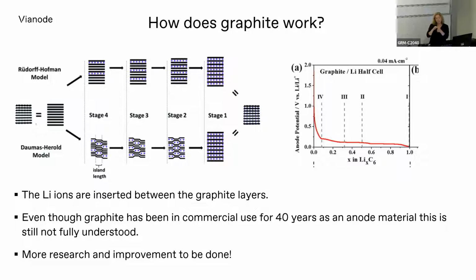And so when you push the lithium ions into the graphite, it goes between those layers of sheets and it sits right in the middle of that ring of atoms. And then that allows it to be stored in a very stable way. So what makes graphite work so well as an anode material is that you're only moving the sheets of carbon atoms a little bit apart every time you charge and discharge. And so the fundamental structure of the material is not changing. So that's what's called an intercalation material, where you can put ions into and out of the structure without changing the chemical bonding between the atoms in the structure. So when you have a material like that, it can be incredibly stable because you're not rearranging those chemical bonds.